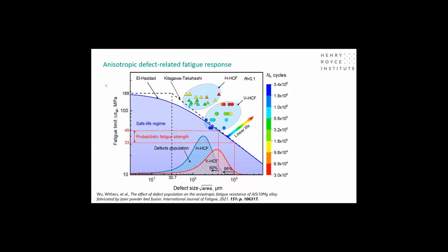And we can see that if we compare the prediction with the measurements, most of the measurements tend to lie outside of the prediction, so that we end up with a safe life regime which can be defined in terms of the defect size and the stress intensity that's applied. We can also see that, not surprisingly, the lifetime increases as you move towards that limit. So shorter lives indicated by red are for the larger defects, and as we decrease the defect size, you can see that the life increases towards the fatigue limit, as shown here.